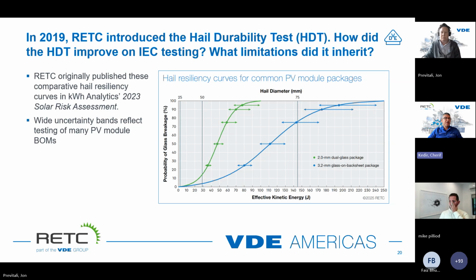And that is noted here, I think, in the graph. What this graph illustrates is hundreds, if not thousands, of modules that we had tested of different constructions. The graph actually comes from a much wider graph that we generated with many different thicknesses, different constructions, different sizes of modules. This one just compares the 2 millimeter construction to the 3.2 millimeter glass construction. And you can see a clear shift in risk of damage between the 3.2 millimeter glass and 2 millimeter glass.